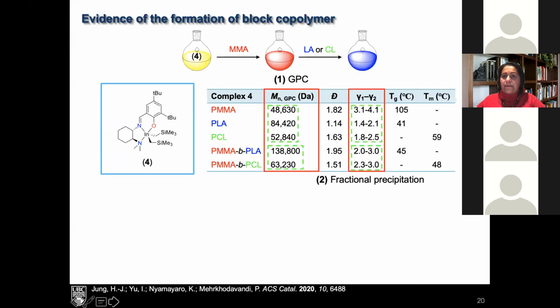So then we looked at fractional precipitation, a technique that looks at the amount of solvent that you add to precipitate different fragments of the polymer. And what we saw was that if we had polymethyl methacrylate, PLA, or PCL, the value Y1 minus Y2, I won't get into this, but it has to do with how much solvent you have to add to precipitate these materials, would be the same as for these other polymers. And it's actually not, it's an intermediate number. So that's the second piece of data. The other one is looking at the glass transition temperature and melting temperature for these polymers. And if you look at the polymers that we're generating, they're somewhat intermediate to what we would expect for PLA, PCL, and polymethyl methacrylate. So that works.